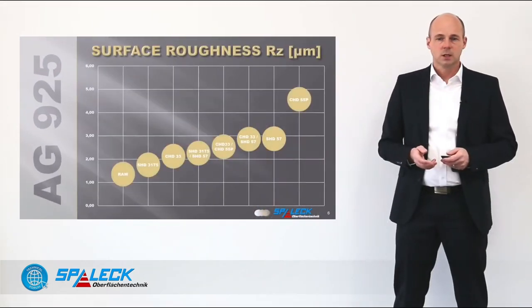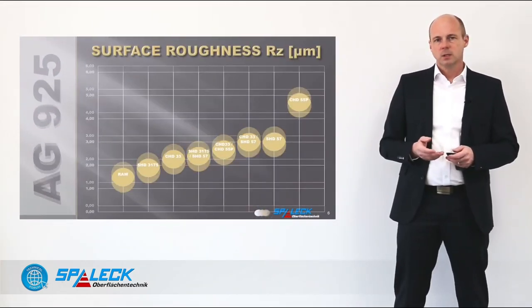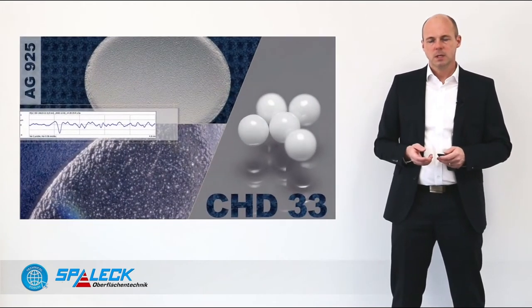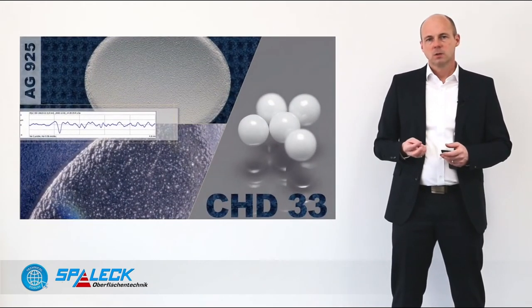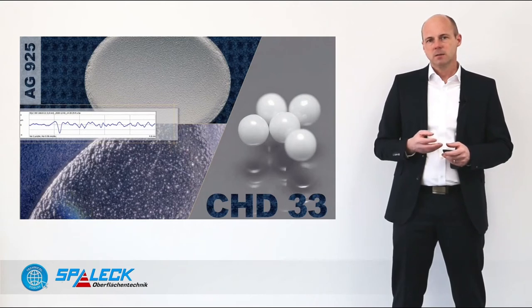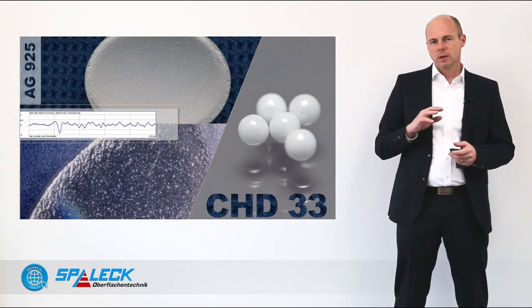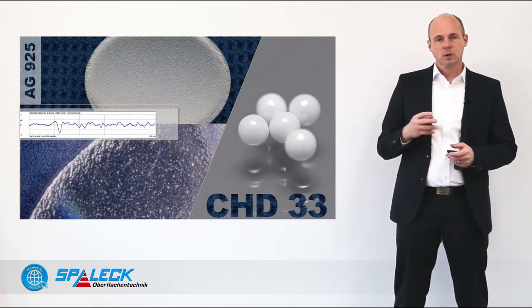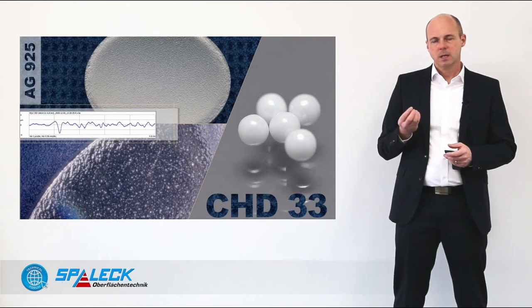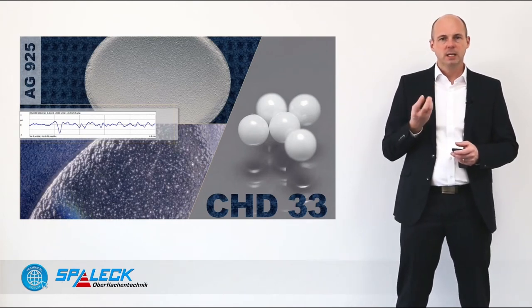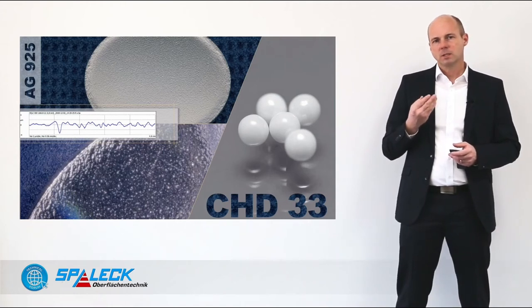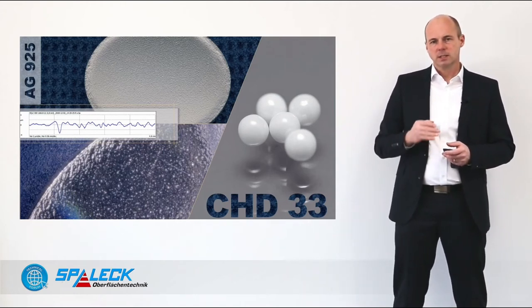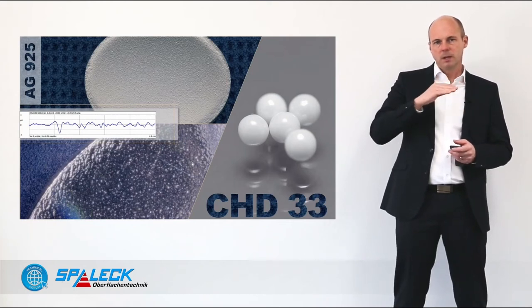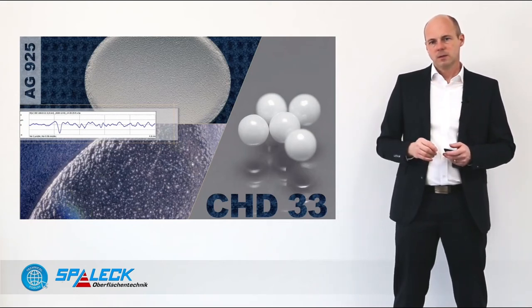A similar effect you can also create with a CHD media. Here we are using balls to again break the texture from the rolling and generate a bright surface. Because we do not have the rim, the blank appears brighter and shinier, because the balls are rolling on the surface instead of ripping off the oxides.